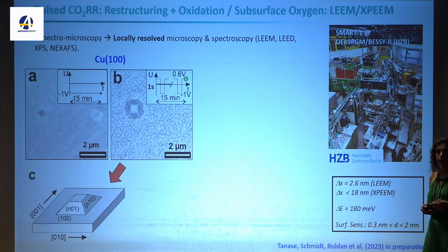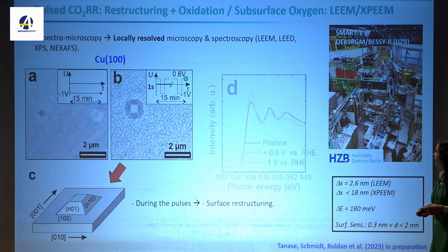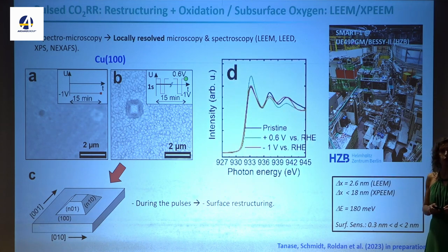So now I can go to my theorist colleague and tell them, okay, the defects that I'm forming, and that are very good for making ethylene, have this structure. They are N10 steps. Isn't it nice, right? Now I can tell them, start with this. It's not 100. This makes hydrogen. It's these structures that I'm creating here which do the CC coupling. And now I can also go locally and do spectroscopic measurements.